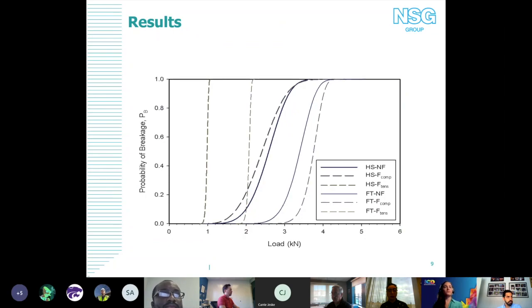So next slide. Here we see just a general layout of our load at failure, or our 3-second equivalent failure load, and our probability of breakage. We're going to focus down towards the bottom, but as a general rule, you see that your control and when frit is in compression have fairly similar failure distributions, at least in terms of the coefficient of variance. You see a similar trend, but once the frit was in tension, suddenly the coefficient of variance significantly reduced. Now you're seeing, okay, whatever is breaking this, it's the same sense of mechanical failure every time. It's happening very sudden. It's happening at around the same stress or the same load every time.